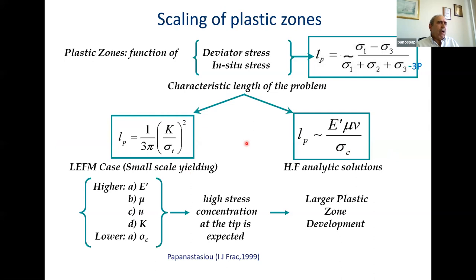Now, how important is plasticity? It depends on the scale of the plastic zones. If the plastic zones are small, plasticity will not be important. So we attempted to scale the plastic zone to see which parameters it depends on. And of course, the first parameter we found is the deviator of the stresses, the difference between the stress along the propagation direction minus the stress normal to the fracture plane. The closure stress is that, as you can see.